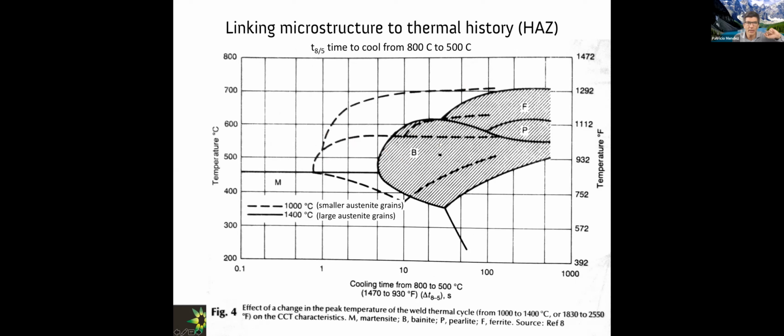The other one that is shaded is more representative of welding, that corresponds to a much higher holding temperature, in which the grain size of the austenite grew very coarse, and because the austenite is coarser, everything slows down to slower times. So same material, but two different initial austenite grain sizes, and they have very different hardenability.